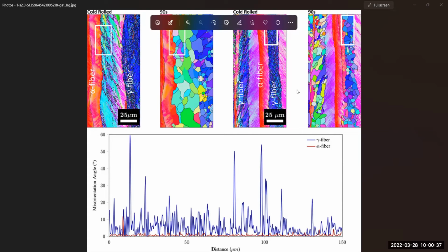So with heat, you can see the new crystal forms, and then the orientation of the crystal matters. In my thesis I had a different work where, based on formulas for magnetization and magnetic anisotropy, I can give you an estimate of how much energy it would cost to magnetize that crystal along the plane. So looking at this, I can just apply that formula. For example, these crystals on the left you might have an easier time magnetizing along the plane, whereas crystals on the right need more energy.